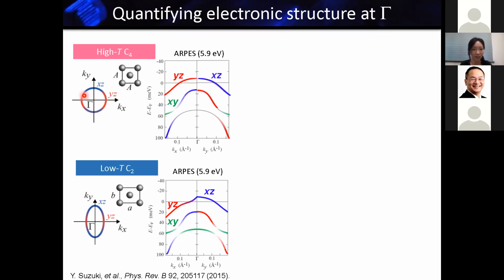But as you can see, it's four-fold symmetric, like this. But when you go down to the orthorhombic phase, you can see that along this short axis, the Fermi surface is composed of this YZ and XZ mixed state. But along this KY long axis, you can see that the XZ orbital is composing this Fermi surface. And the Fermi momentum becomes very different along KX and KY. So this is what's happening in this nematic state.